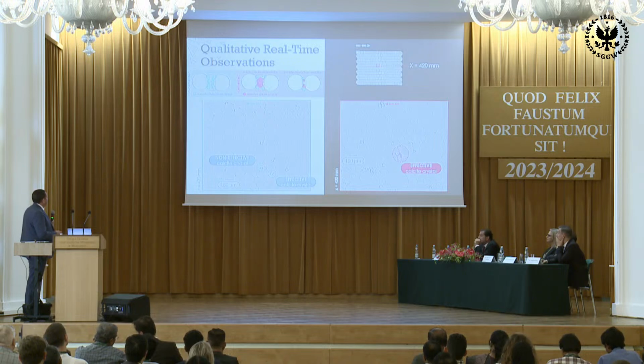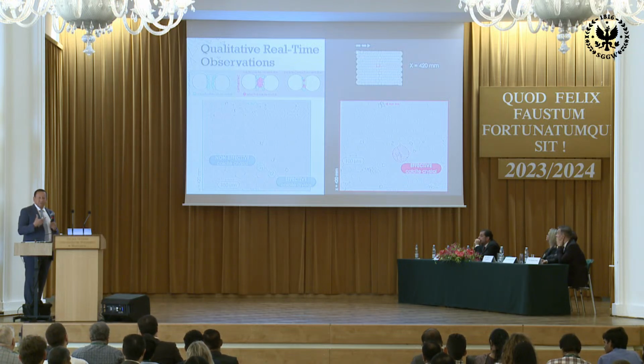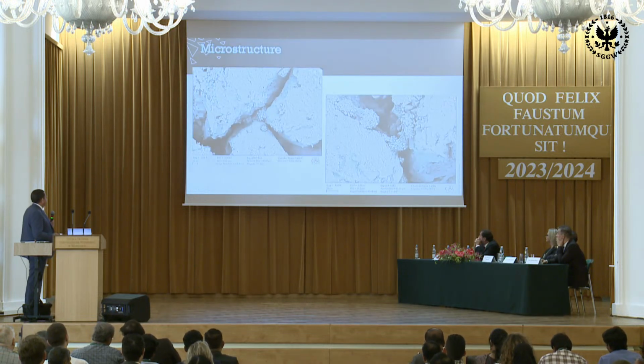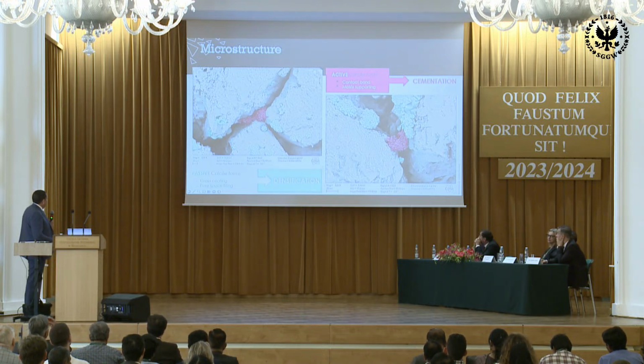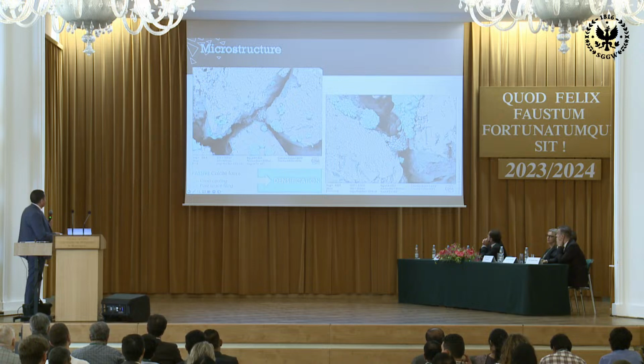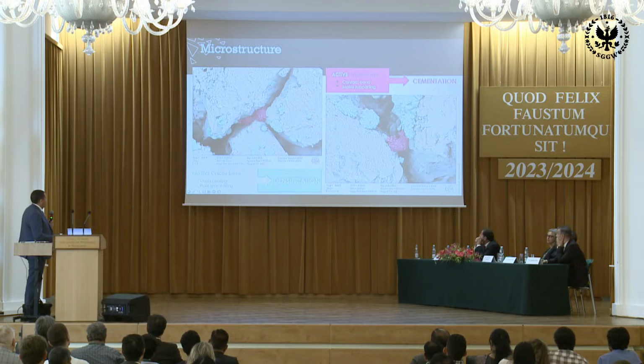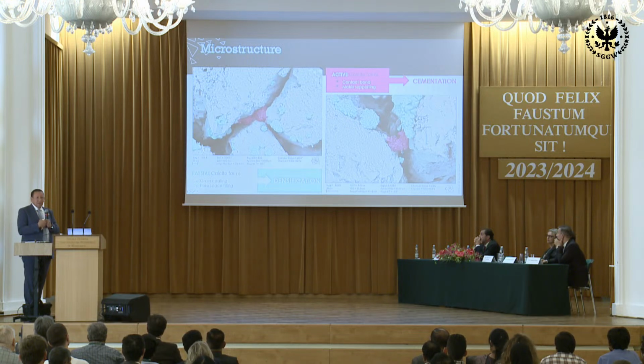There are those two rheological processes that we would now like to introduce in a constitutive way, to be able to represent the evolution of the behavior of the material with biocementation. Here it's another scale that I'm taking. We took those pictures just to show you that, from one side, we see those elements of calcite that are not creating glue but densifying the material. And from the other side, we have this cementation that is happening by putting the grains in direct contact, creating this biocement.